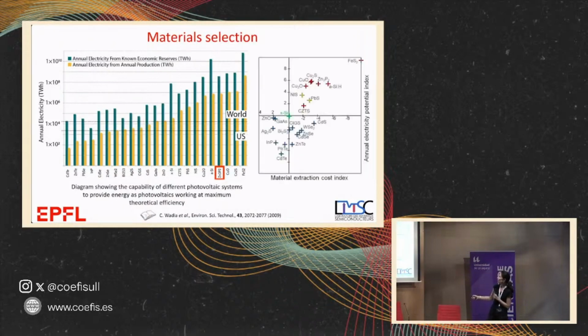You can look at another graph that tells you the material extraction cost index and the potential for producing electricity. So to create a new material that serves, you need to make sure that the extraction doesn't cost much, and it has the potential to have high efficiency. Crystalline silicon is here in the middle. You have gallium arsenide here, and you have zinc phosphide here. So we decided to work on zinc phosphide for this reason, but there was very little literature on this.